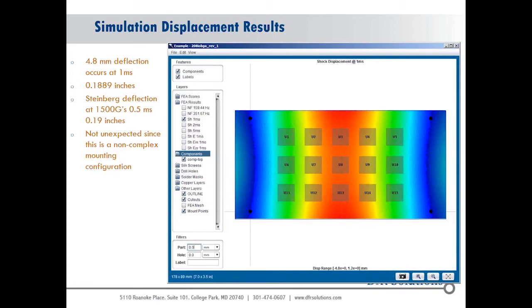So, it's a half millisecond pulse. The maximum deflection of the circuit board doesn't occur until at 1 millisecond. So pretty much the shock pulse is done, and then the board is actually starting to catch up to it. The other thing to show is that the FEA is showing about 0.2 inches of deflection, and if I know the natural frequency, I can actually get a very good deflection value out of the Steinberg prediction of about almost the same number.